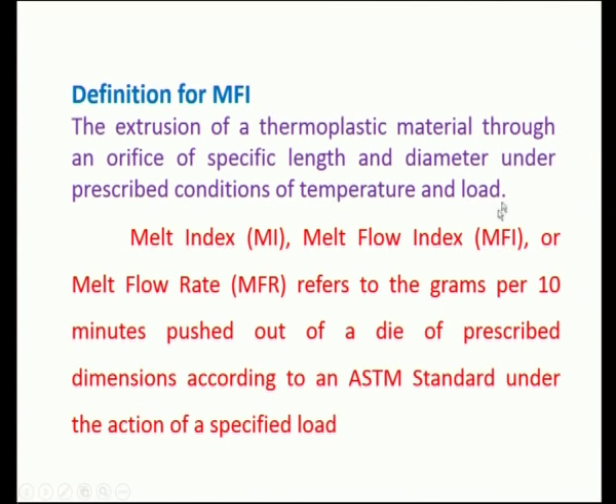Similarly, the load, whether you have to maintain a 1 kg load or a 2 kg load, and what should be the length of the orifice through which the polymer is extruded, and what is the diameter of the orifice through which the polymer will pass. In other words, it is also called melt index, melt flow index, or melt flow rate. All these are collectively called MFI. It simply means how many grams are extruded per 10 minutes, pushed out of a die of prescribed dimensions according to an ASTM standard under the action of a specified load.